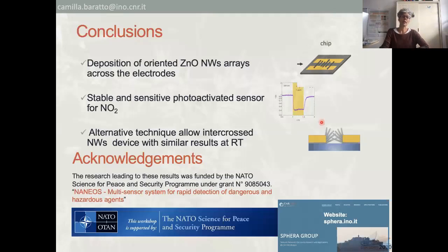So concluding, we were able to deposit oriented zinc oxide nanowire arrays across electrodes, which can be tested for sensing application. And the condition we selected was working at room temperature with UV activation, which allowed us to detect low concentrations of NO2. This is also interesting for developing a sensor which works for explosive conditions where temperature is not wanted. And also we tested this alternative technique for making an intercrossed nanowire device, which also can be exploited for sensing.